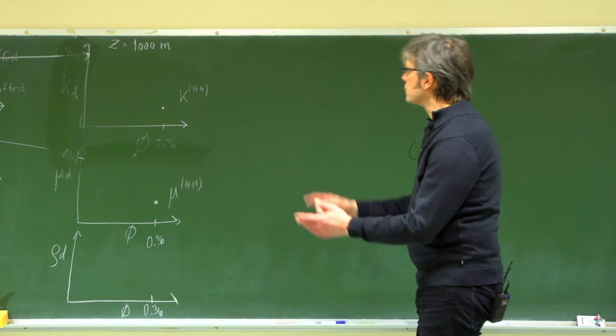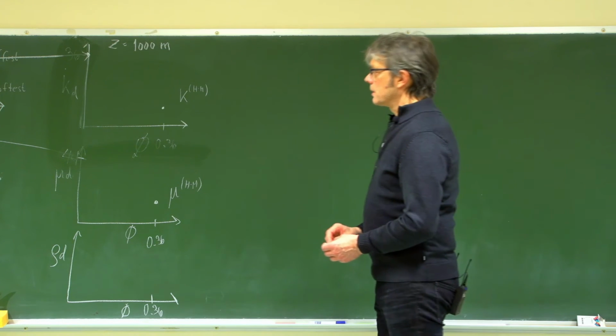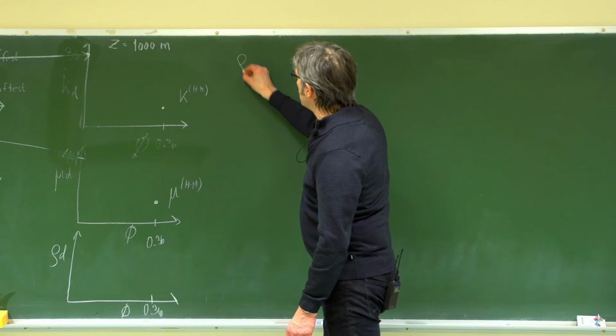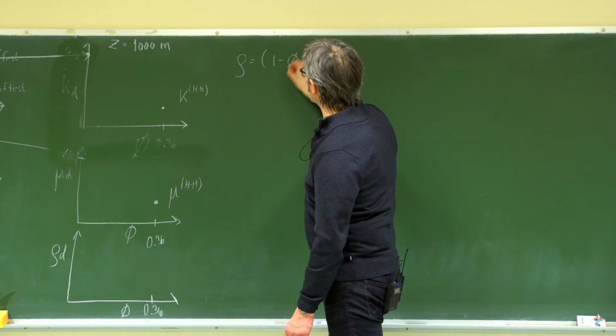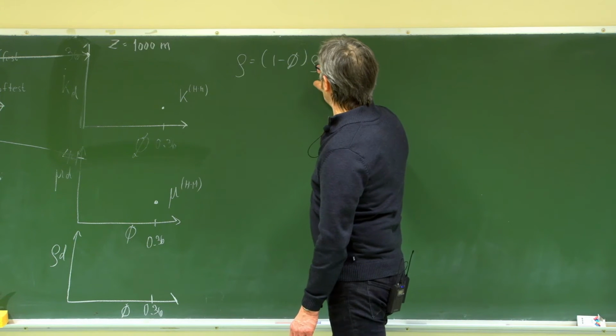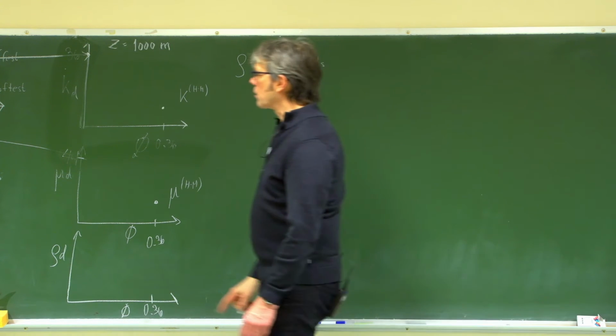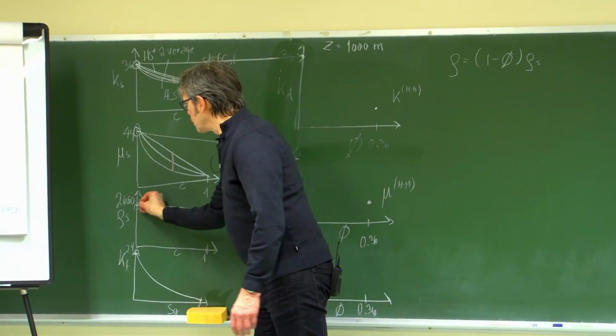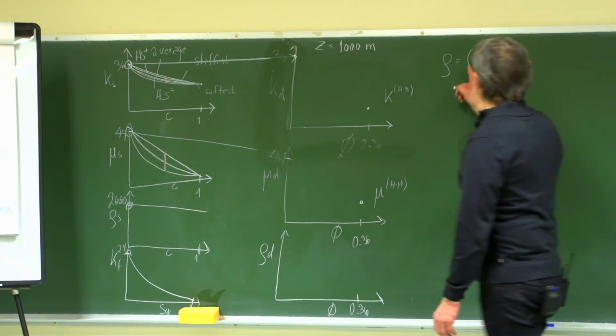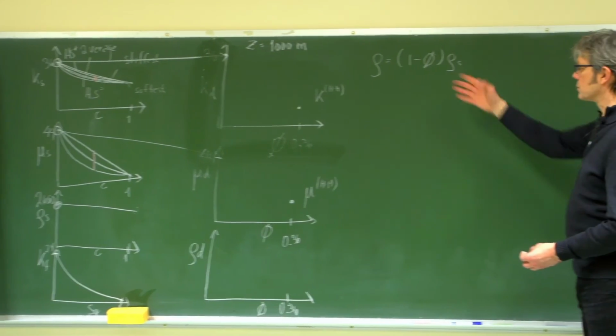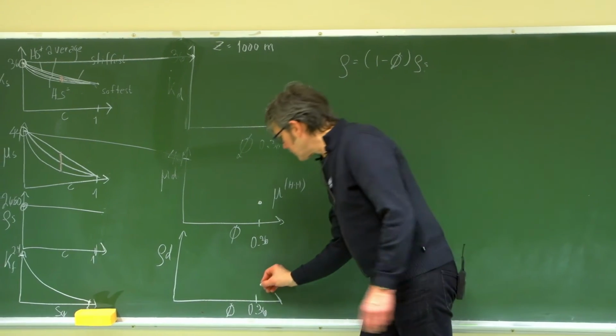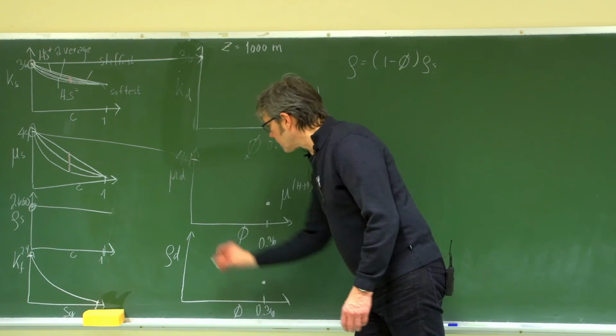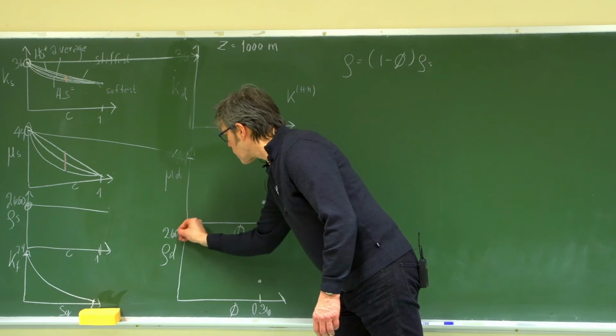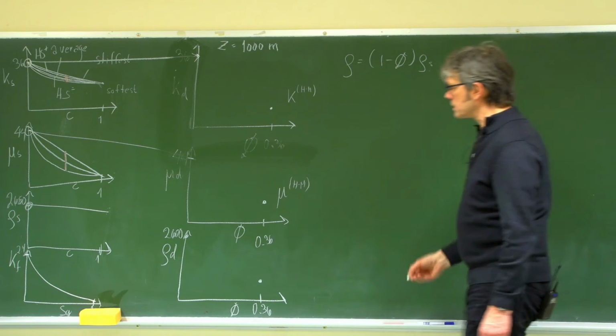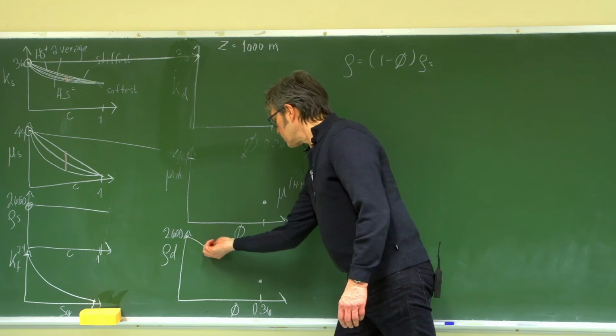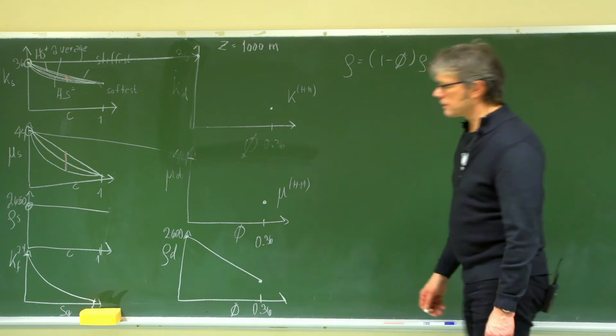However, the density is very simple to calculate here. I could just use effective density = (1 minus porosity) times the density of the solid. And of course, our solid here is 2.65. Since we have no fluid, it's just one simple line here. So it would be down here, and the other point is up here, 2.6. And we immediately see from this equation that the dry rock density would just be a straight line like that.